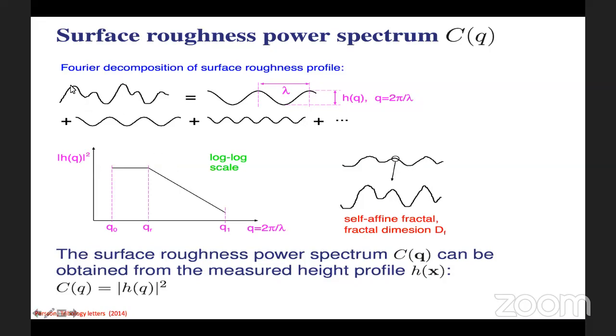If you measure surface roughness, suppose using a stylus instrument, you can decompose this surface roughness into a sum of sine and cosine profiles having a height amplitude and a wavelength. Then you can plot the square of the height amplitude versus the wave number. The wave number is equal to 2 pi upon the wavelength. If you plot the square of the height amplitude with the wave number, you will form what we call the power spectrum. This power spectrum contains all the information that is needed to know about a surface and its roughness characteristics.